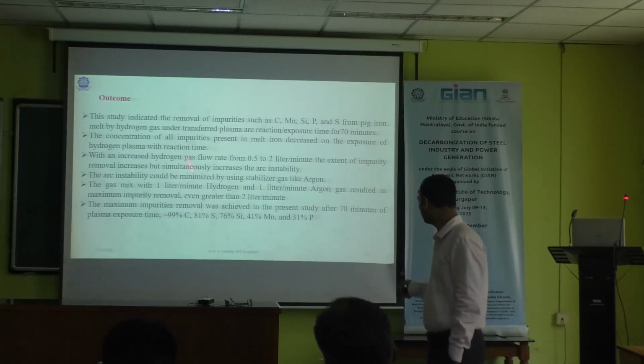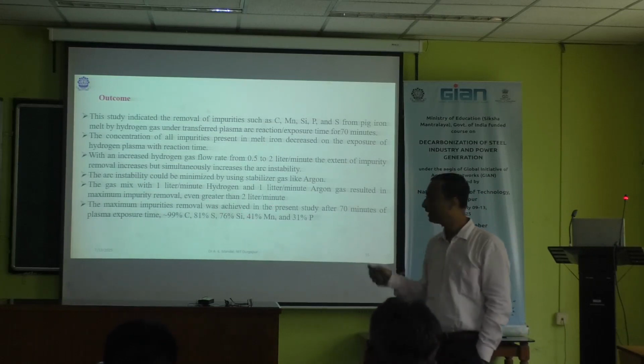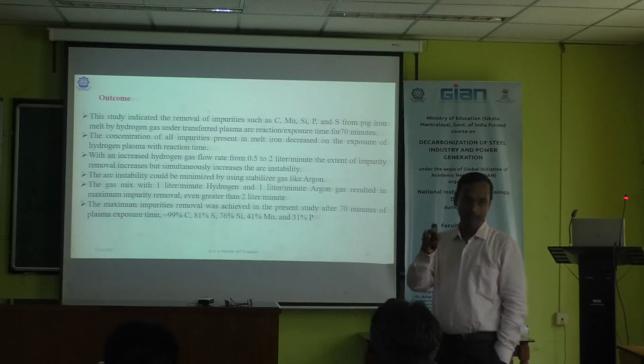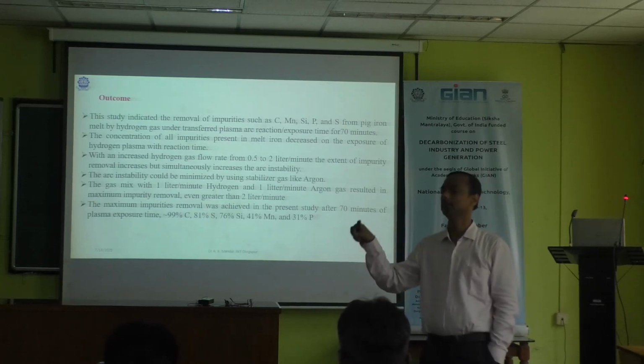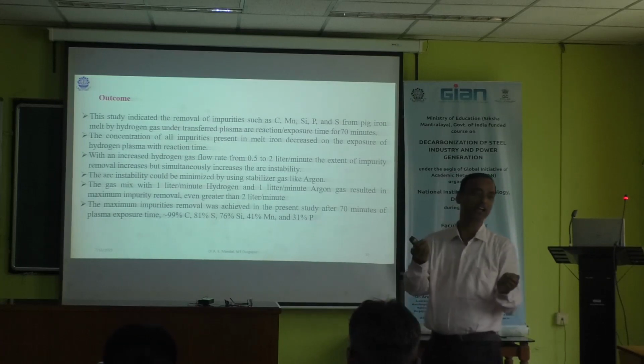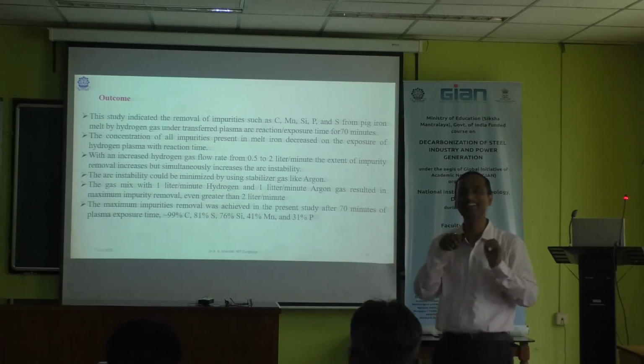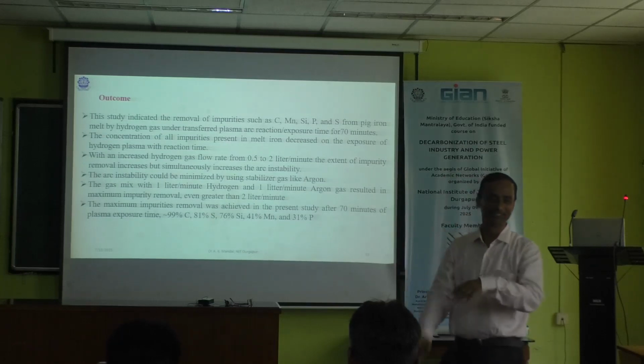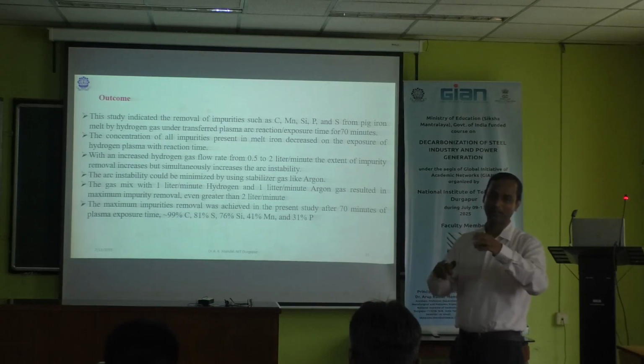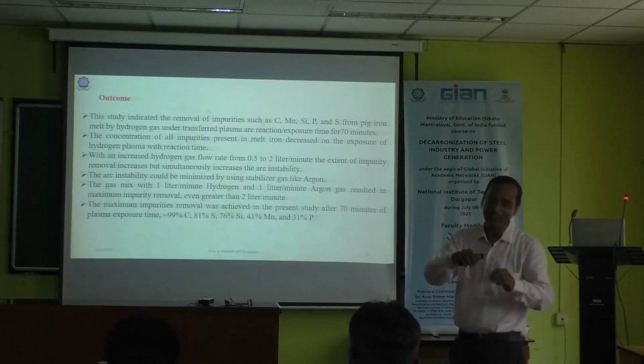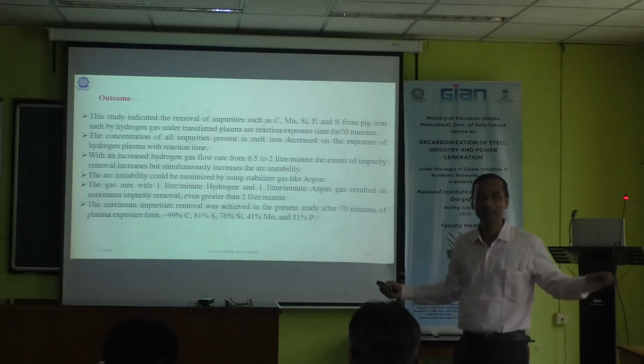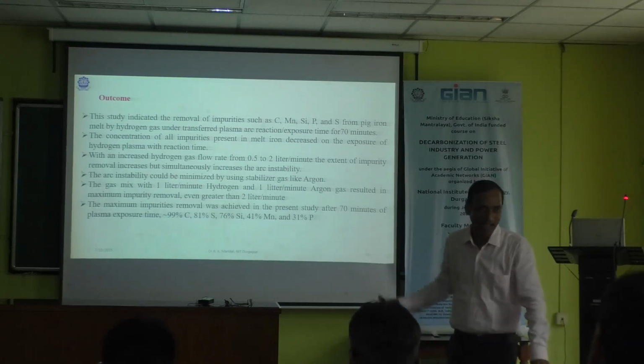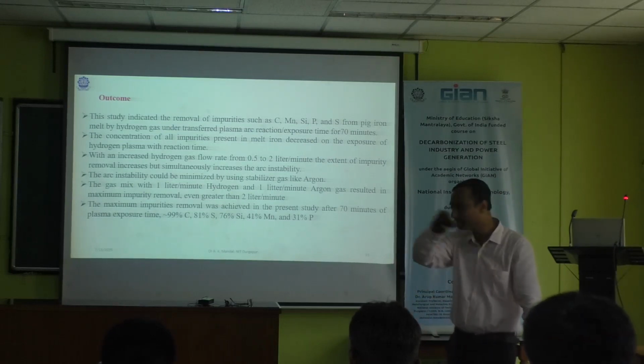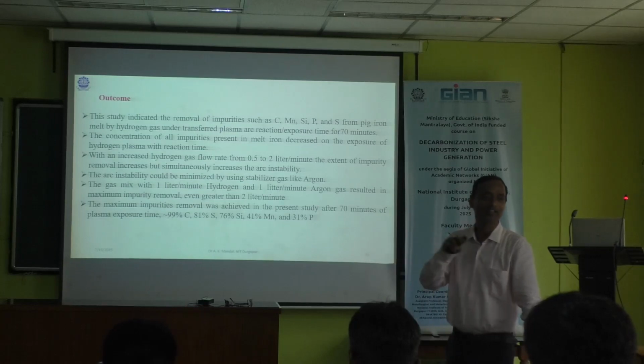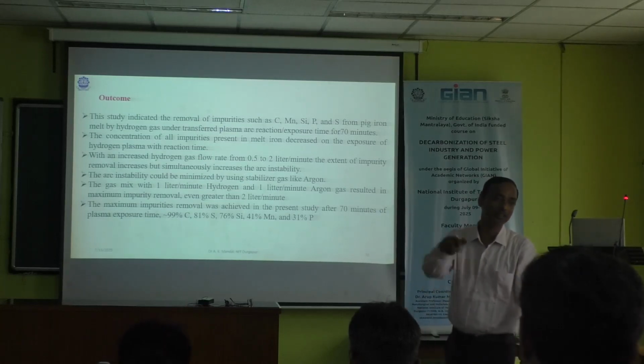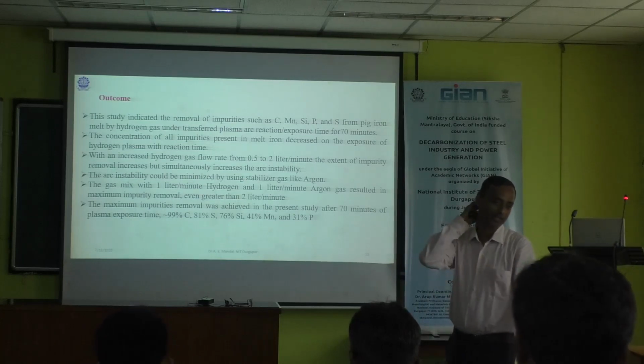So why is this manganese and phosphorus removal less? If you see manganese, actually in our system, the kinetic study requires sampling at regular intervals. When you open the lid, there will be some air entrapment inside. Because at that time you have to stop the gas, and when you stop the gas and remove the lid, there will be air entrapment. Air contains oxygen, and it will produce a manganese oxide layer at the surface. This creates a problem for further removal of manganese.